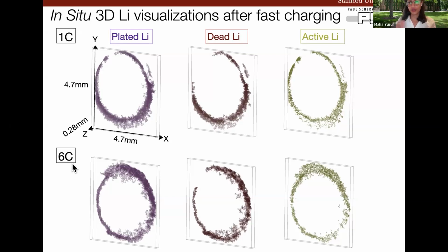The first thing I notice in this data is that when lithium plates, it doesn't plate like a chunk of lithium metal. It does have a certain degree of porosity associated with it. For example, you can see these nodules of different degrees of density. And sorry, I didn't explain the difference between plated, dead, and active lithium.